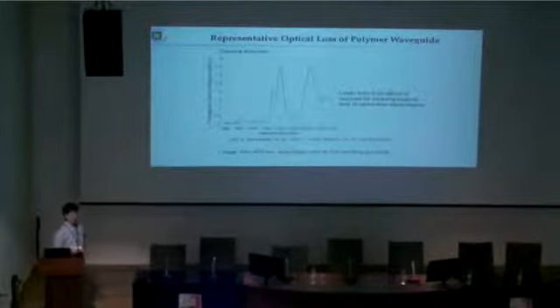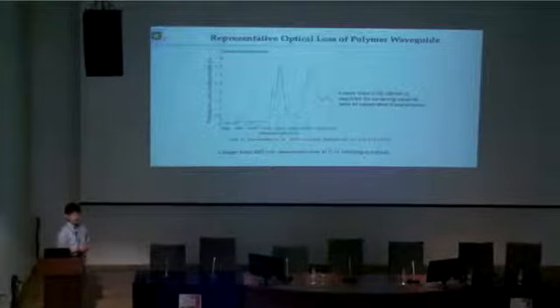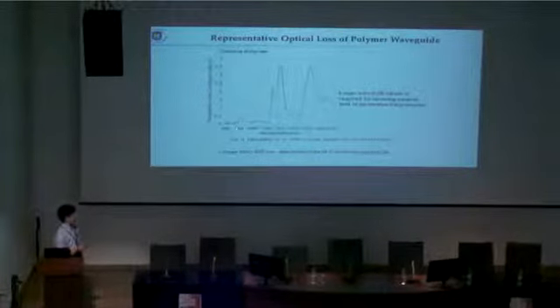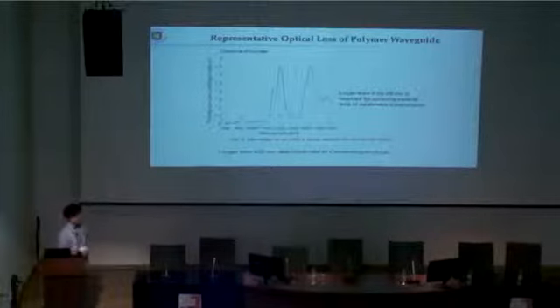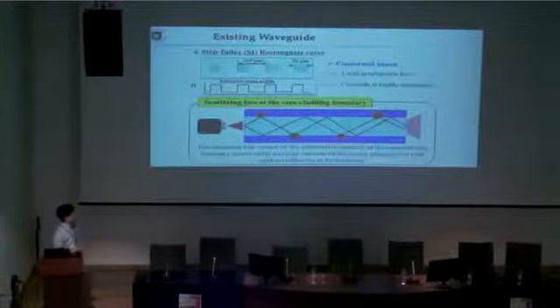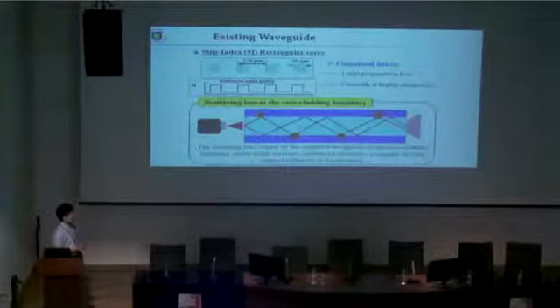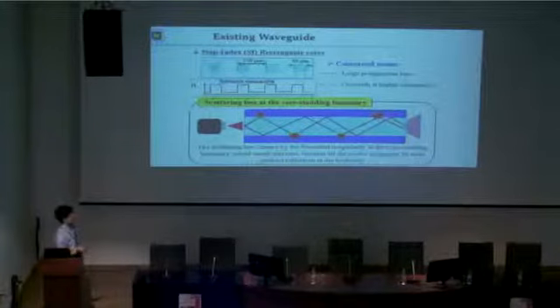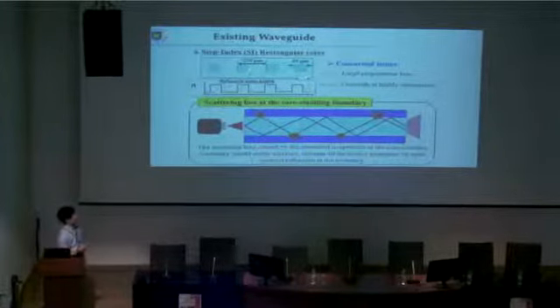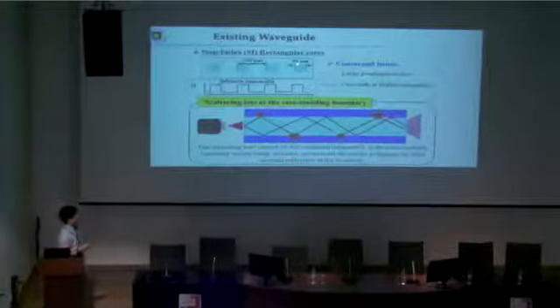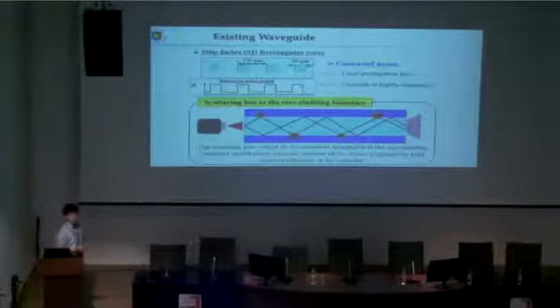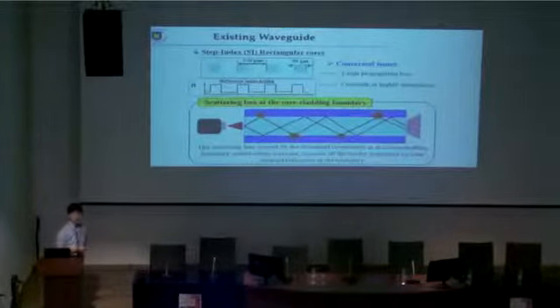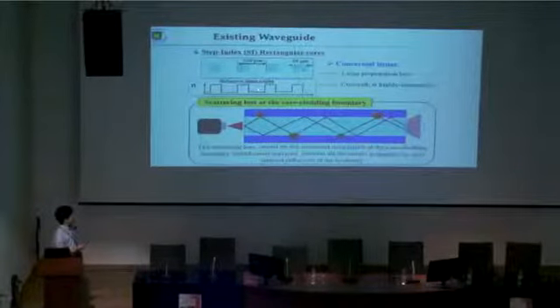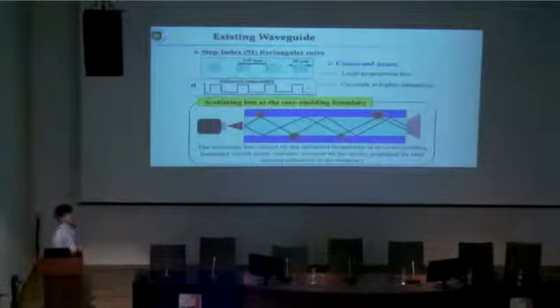However, for multimode applications, normally VCSELs emitting at 850 nanometer are widely used. Therefore, we do not have to care about the attenuation at longer wavelengths here, and we are mainly focusing on this 850 nanometer wavelength. And because of the specifications I mentioned, in general, multimode polymer waveguides have these structures. Normally, the core has a square shape like this, and the core size is 50 micron times 50 micron, or less, like 35 micron. And the refractive index in the core is flat. We call this structure a step index type.